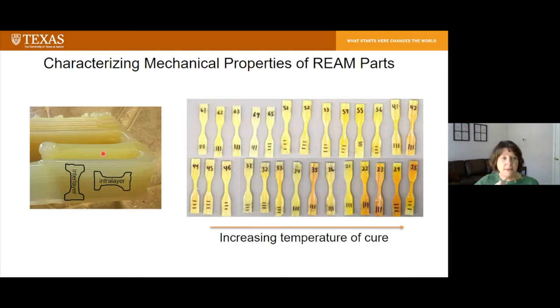Here you can see we built some vertical walls, and from that we machined tensile bars. You can see an array of them on the right. The little black hash marks that are either vertical or horizontal indicate the direction of the layers in those parts, so we know whether we're stretching them parallel to the layers or across layers. You can also see that some of these parts have different colors, and that's going to turn out to be important because the darker colors indicate a greater degree of cure, and that's going to have some influence on the strength of these parts.